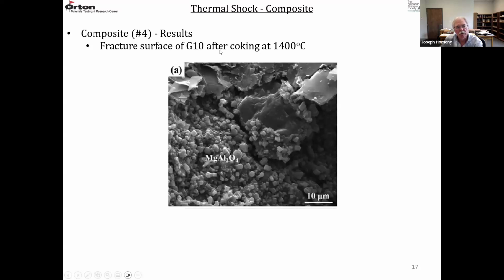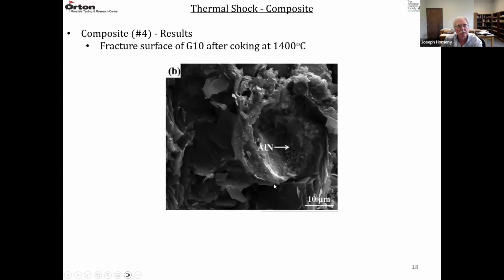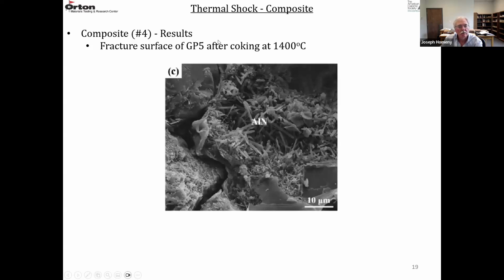And this is G10 after coking at 1,400. Again, showing these spinel crystals forming on the surface of MgO aggregates. So G10 had no pellet additions. And a little bit higher magnification of G10 at 1,400, showing these aluminum nitride whisker, needle-shaped crystals forming. And then this one is GP5 after coking at 1,400. You can more clearly in this one see the needle or rod-like shaped aluminum nitride crystals.